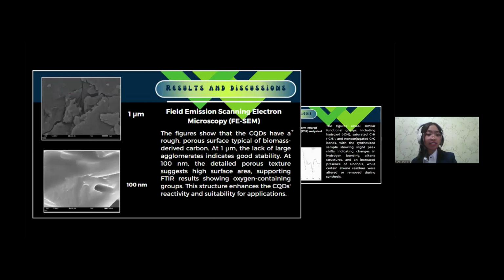These figures show FESEM images of the CQDs. At 1 micrometer, the surface is rough and porous but uniform, indicating good stability and successful synthesis. The texture reflects typical carbon materials from biomass, with small clusters sticking together. At 100 nanometers, the porous surface provides a high area for oxygen-based functional groups to attach, supporting the FTIR findings as shown before and showing the CQDs' reactive surface.